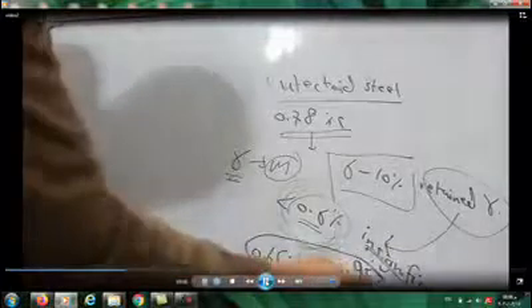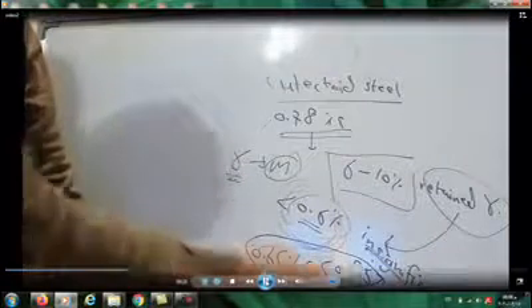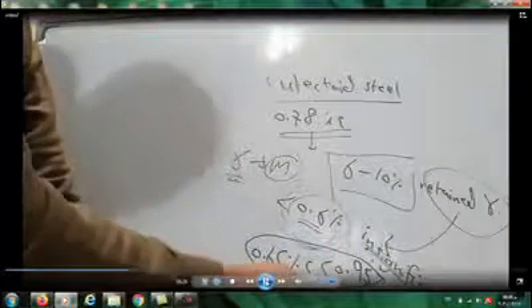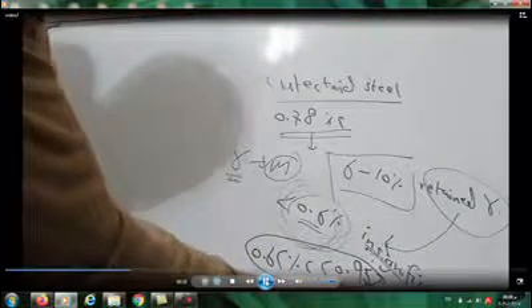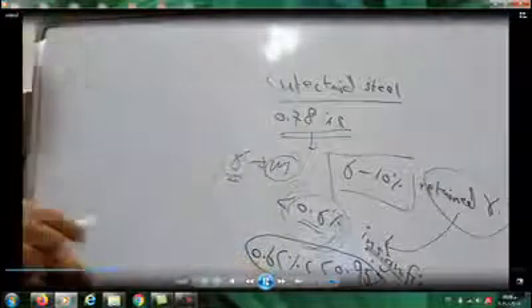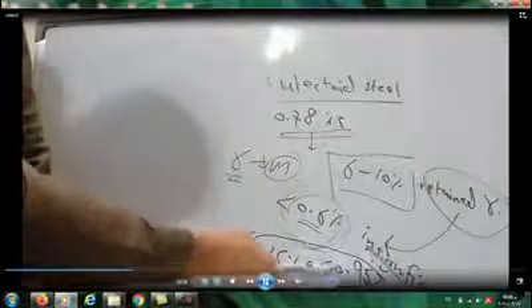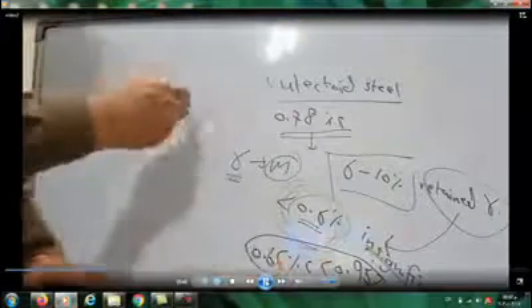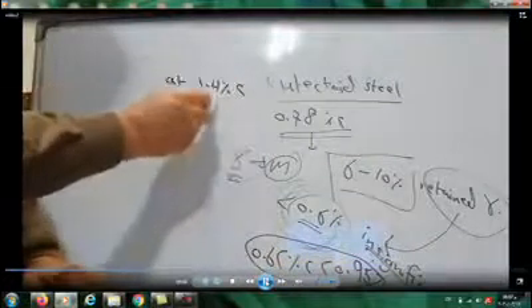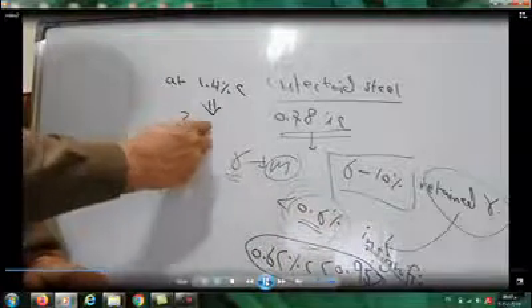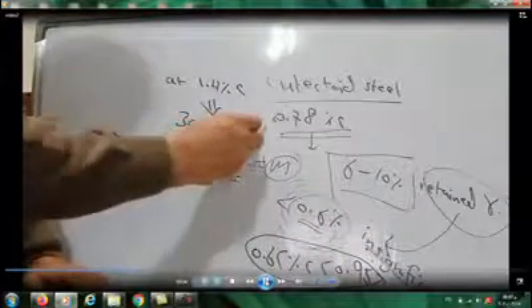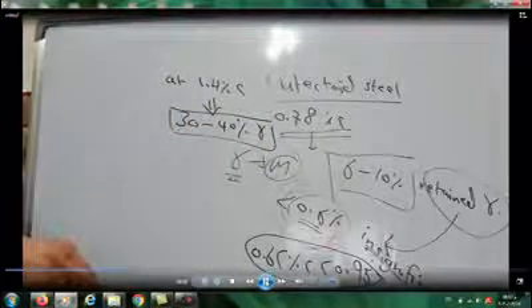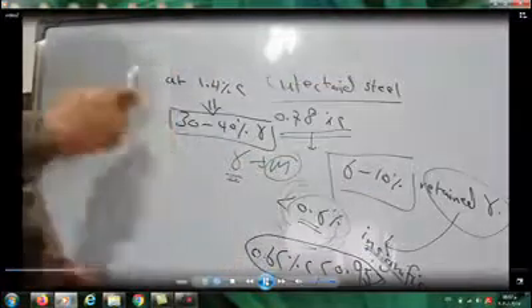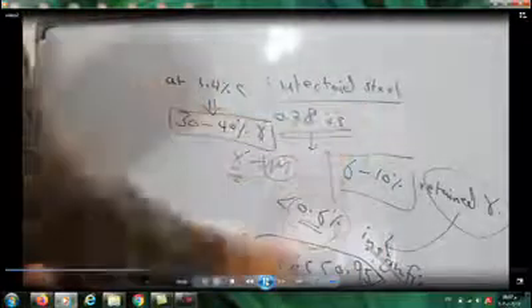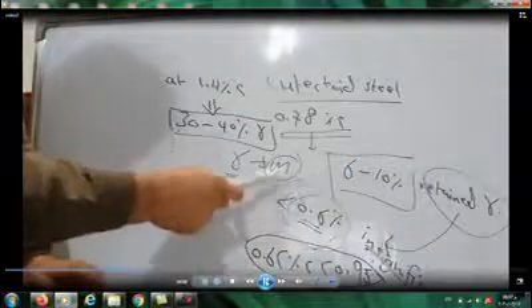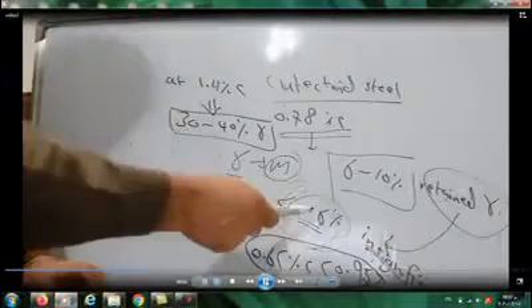They found that if the percent carbon is within this range, there is almost 10% retained austenite. Of course, after this percentage, for example at 1.4% carbon, they found a very high percentage of retained austenite. So from these notes, من هاي الملاحظات, the relationship between the retained austenite and the percent carbon.